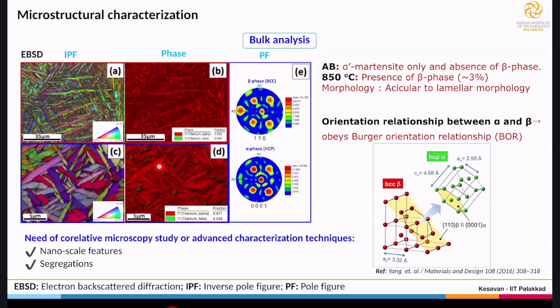Fine. So you can see that at 850 degrees Celsius, the beta fraction has come out from the supersaturated solid solution, shown in green. This volume fraction is about 3% in this case at 850, and it increased to 6% at 950 degrees Celsius. With further analysis, we also noticed that this alpha and beta obey the Burgers orientation relationship.